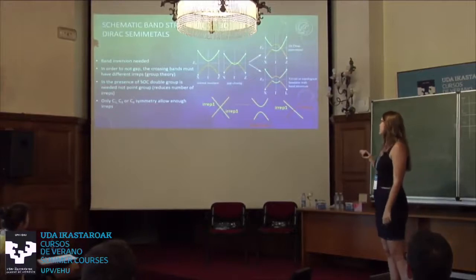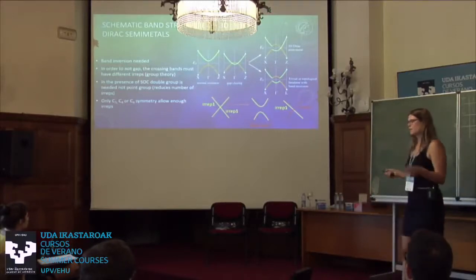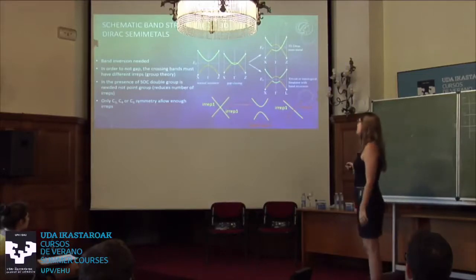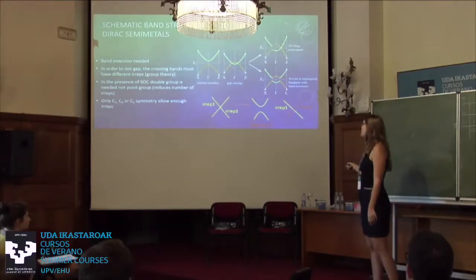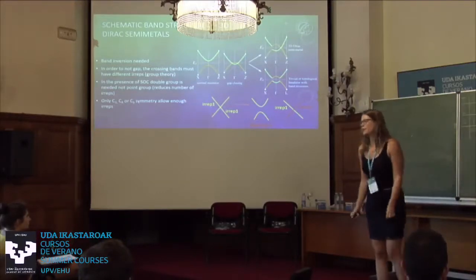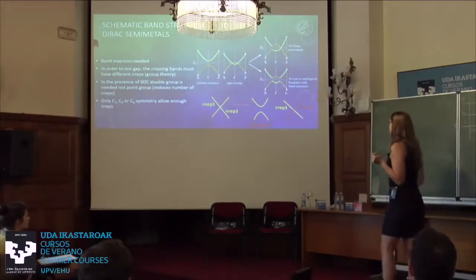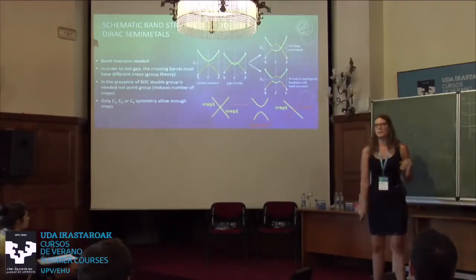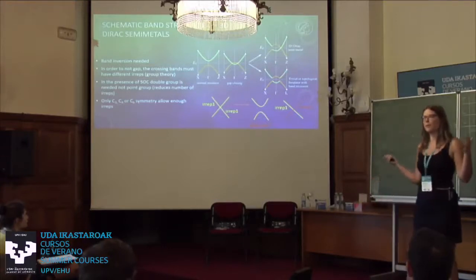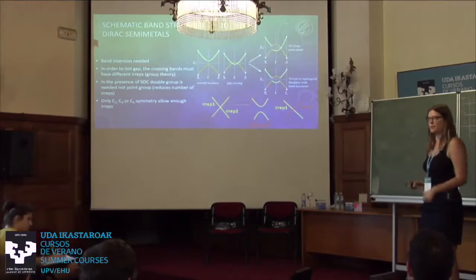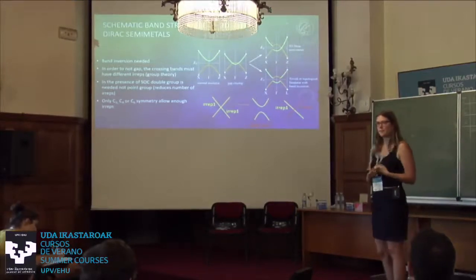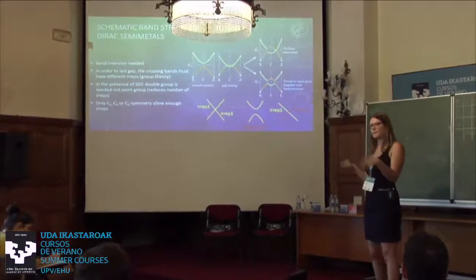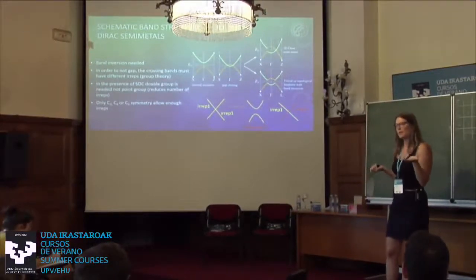So if you look at the normal band structure of an insulator where you have a band gap, just think about decreasing the band gap, maybe by putting heavier elements in it or decreasing the electronegativity difference. You can have this kind of band structure with a band inversion or a negative band gap. And then you have those two crossing points where the bands cross. And the question is, is this crossing allowed or forbidden? This depends on the irreducible representation of the band. So it depends on group theory, so on symmetry, but also on orbital character of the bands. Okay? The orbital character is a little bit sketchy. That doesn't really help us, but the symmetry can help us a lot.